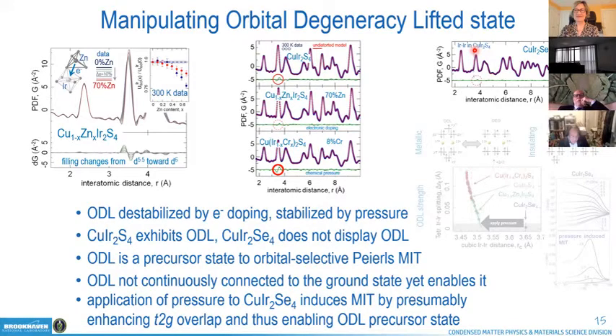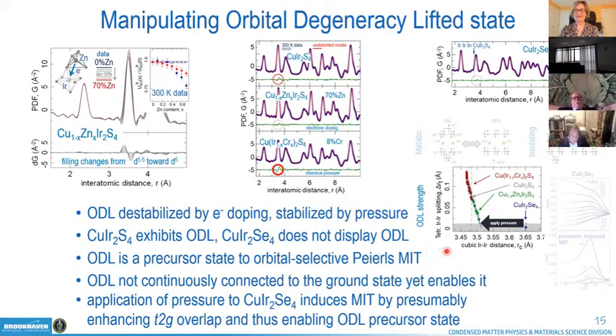Fine. So we have assessed or quantified the distortion associated with this state by fitting a tetragonal model. I don't have time to go into those details, but I'm just going to say that this is the distortion assessed through this modeling as a function of nominal cubic iridium-iridium distance. And what you can see is that you can actually drive this distortion up and down and basically get rid of it completely as you dope electrons, in this case by substituting zinc, or you can actually pressurize it and increase it.